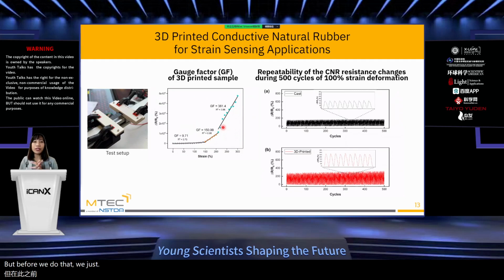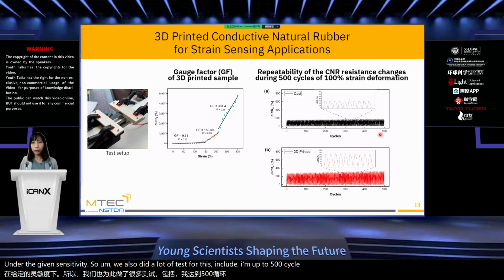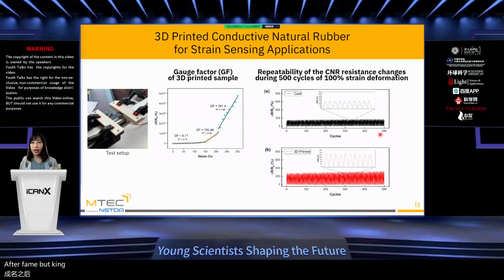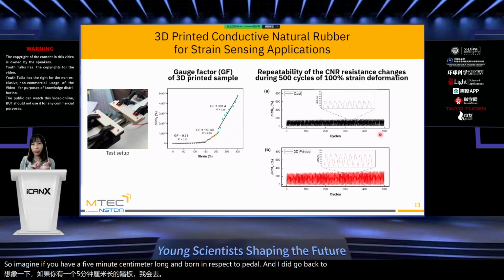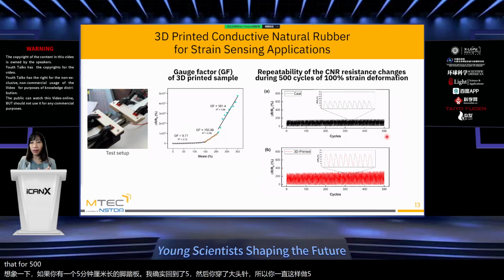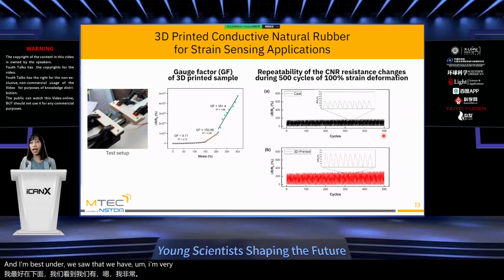But before we do that, we just need to make sure that our material is reliable enough under the given sensitivity. So we also did a lot of tests. This includes up to 500 cycles of the same stretching, up to 100% strain. Imagine you have a 5 centimeter long sample, and you stretch it to 10, and then you go back to 5, and then stretch it to 10. You keep doing that 500 times. And based on the result that we have, I'm very happy with it because it shows a very reliable and robust cycle.